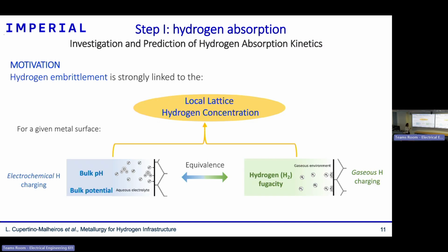All right, we have then 2 environments. So to be able to do a full prediction of hydrogen embrittlement, for a given metal surface exposed to an aqueous electrolyte, we should be able to predict how much hydrogen enters inside the alloy based only on known bulk parameters of this electrolyte. They are usually pH and potential.